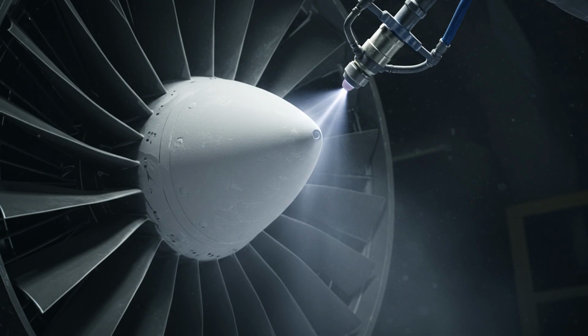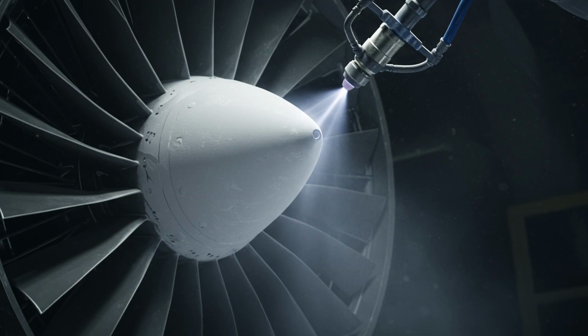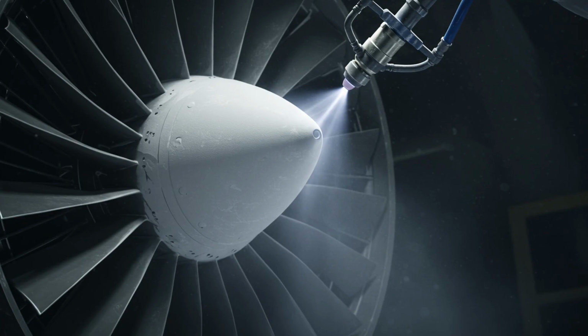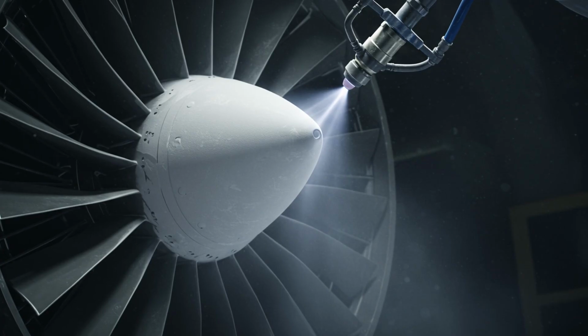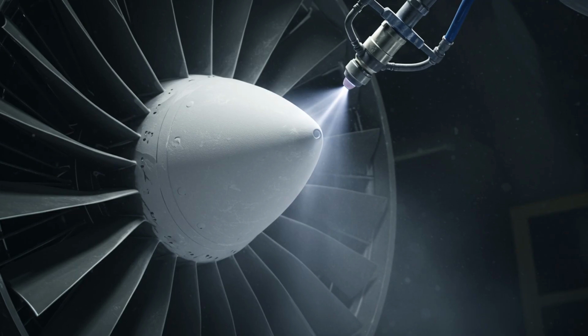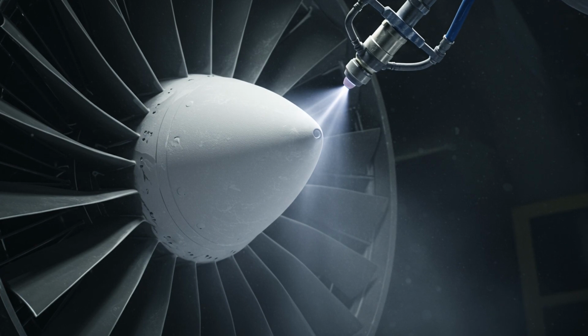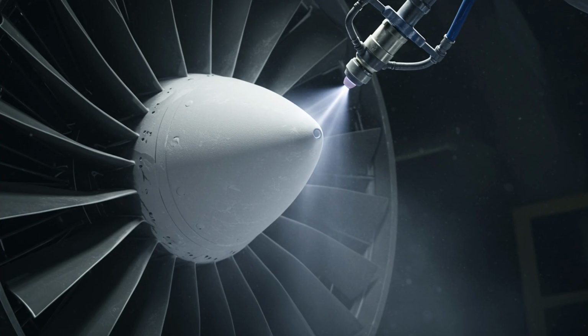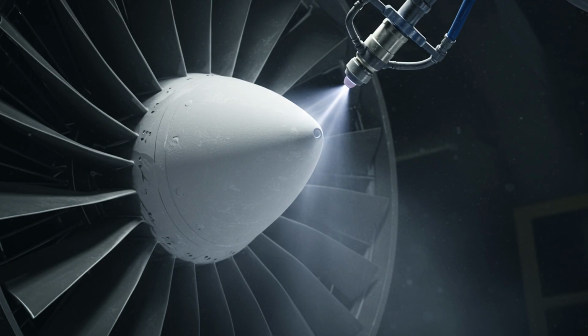This ceramic layer is only about 200 micrometers thick, roughly the thickness of 2 sheets of paper, but it acts as a powerful insulator. It creates a temperature drop of up to 300 degrees Celsius between the hot gas and the metal surface. This coating has a structure like microscopic columns, allowing it to expand and contract as the blade heats up and cools down without flaking off. Without this invisible ceramic armor, the metal would lose its structural integrity almost instantly, turning the engine into a molten mess. It is the same technology used on the heat shields of spacecraft re-entering the atmosphere, repurposed to keep you cruising at 35,000 feet reliably and safely for thousands of hours.